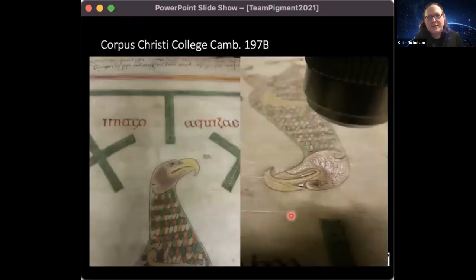This one's probably the best one to illustrate. So even looking down the microscope at this one, you can see that all the areas of pigment have a black line or an area of blank parchment between that line and the pigment to keep them separated. And a lot of insular art is very much using that technique for all the pigments, not just the ones that they know is going to go black, so it's consistent across the whole thing.